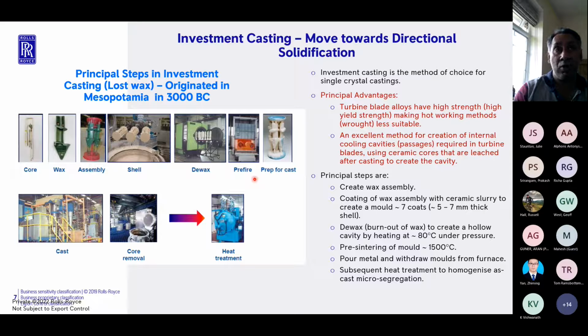Turbine blade alloys are a lot stronger, simply because the typical operating temperature of a turbine blade is roughly about 900 to about 1000 degrees, maybe 1050. The operating temperature of a disc is about 650 to about 700 degrees, 700 to 800 degrees. So clearly you've got about a 400 Kelvin deficit in temperature that a disc is meant to operate at compared to a blade. So blade alloys are definitely stronger. So the stronger the alloy, the harder it is for you to thermomechanically process it. So therefore, that immediately cuts out the forging route altogether.